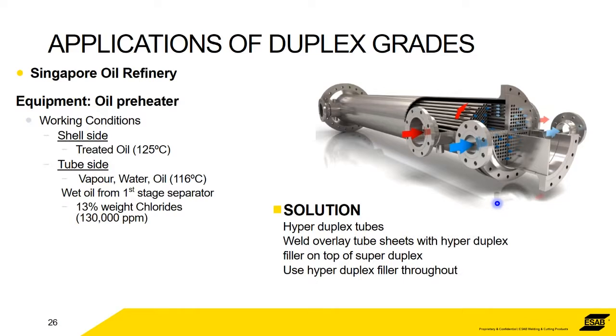This hyperduplex is available in tubes, which we used for the heat exchanger tubes. The tube plate was a clad plate with super duplex and then hyperduplex, and then everything was welded together with hyperduplex. Please, I'm not trying to suggest that hyperduplex is a replacement for alloy 625, but in this application the corrosion was from chlorides, and chlorides are perfect for duplex structures. They have very little effect on duplex structures. And because the temperature was at 125, if it had been at 500 degrees, then it wouldn't have been any good. But in this application, it was fantastic.